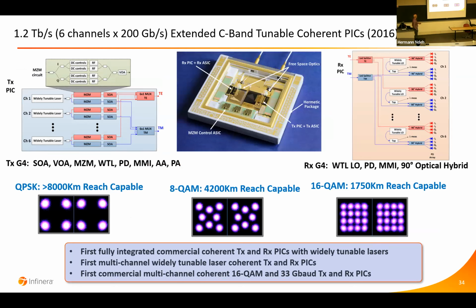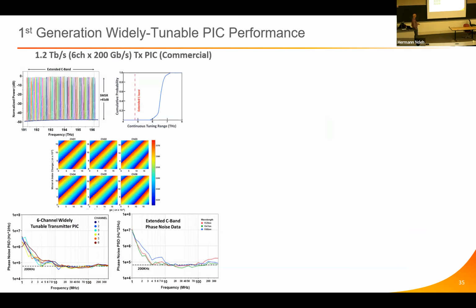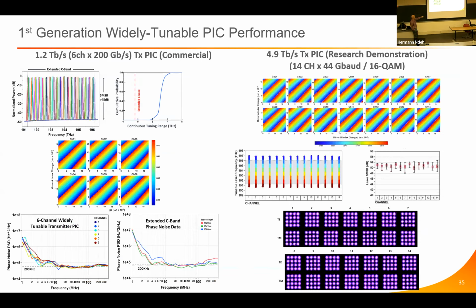We ultimately also developed tunable lasers on this technology. Again, this will be a little bit relevant relative to where we're headed in gallium nitride. With those tunable lasers, we can tune over 50 nanometers in the infrared. In this case, we integrated 6 lasers on a photonic IC in a commercial product. In the research lab, we integrated 14 widely tunable lasers, and that gave a capacity of almost 5 terabits per second on a single chip.